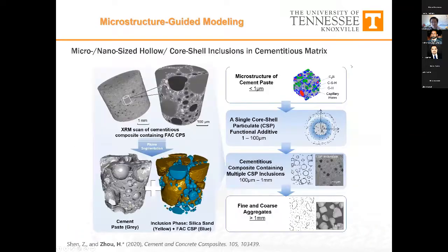So in my group here at University of Tennessee, we have developed a computational framework that takes the multi-scale nature of cementitious composites, and we can basically cross the different scale boundaries in looking at, for example, the microstructure evolution of a cement paste with different cement formulations, the ones that involve CSA cement or slag or fly ash and so forth, to generate a microstructure and homogenize to effective properties that can be passed down to the next level.